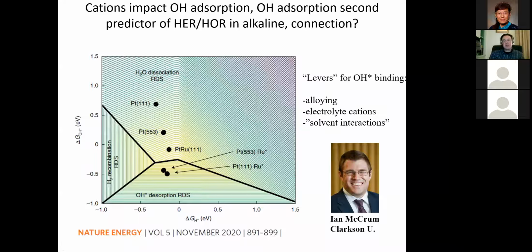This gives us additional levers now to make better hydrogen oxidation or hydrogen evolution catalysts. We don't just have to play with the metal. Now, of course, Ian's results, the best, the nicest indication of this on the previous slide, did do this by depositing a second metal at a step. But you could also do this then with electrolyte cations, and I showed you that earlier. Perturb the OH binding and then perturb the hydrogen oxidation rate. And you could, in general, use solvation interactions to play with the ability to dissociate water at the surface. So surface additives, organic molecules, different solvents or mixed solvents, all possible ways to alter hydrogen evolution or hydrogen oxidation.